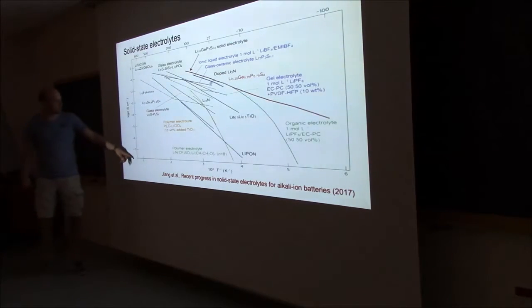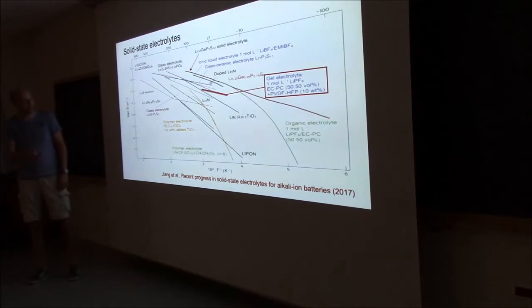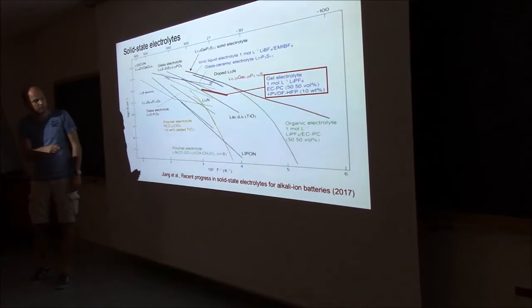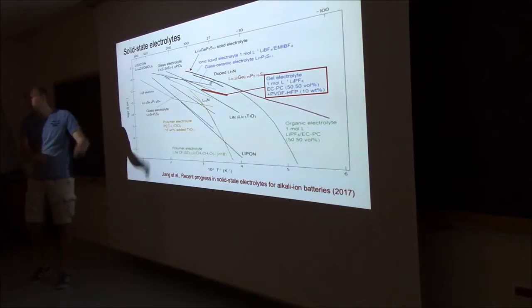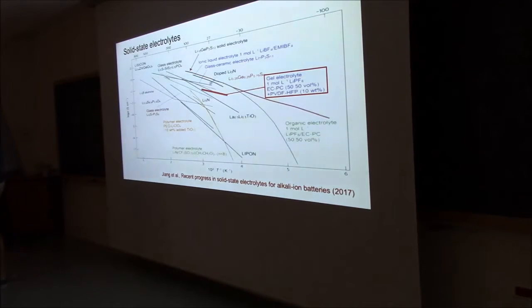If you put it in context, these are the ionic conductivities. This is the temperature on top. This is 1/T. And you can see all of the different materials that I've shown you before. This is where normal liquid is. It's in the middle, and it can only be successful in a small temperature range. That's why if you have heat being created in the battery, you also have problems. And this is where the perovskite is. So maybe at room temperature it's a little bit worse in ionic conductivity, but you can also make it much thinner to compensate for that, but it's reasonable.